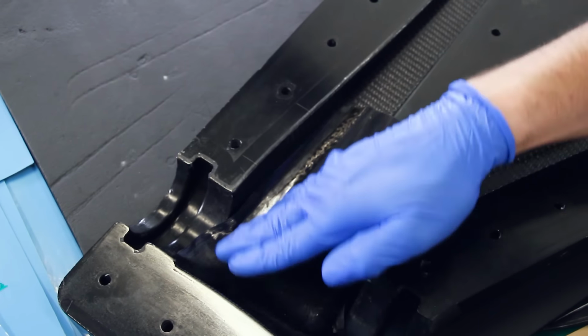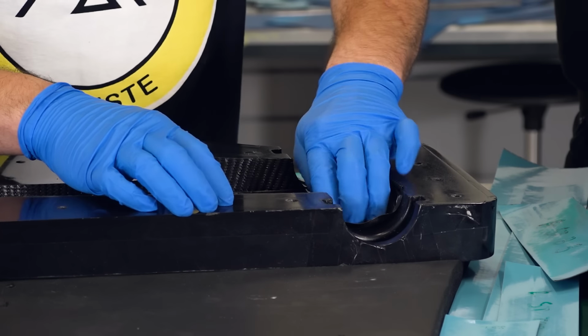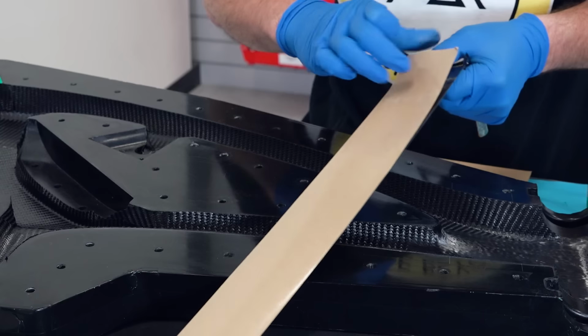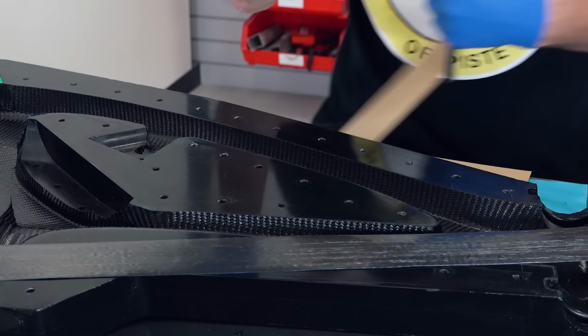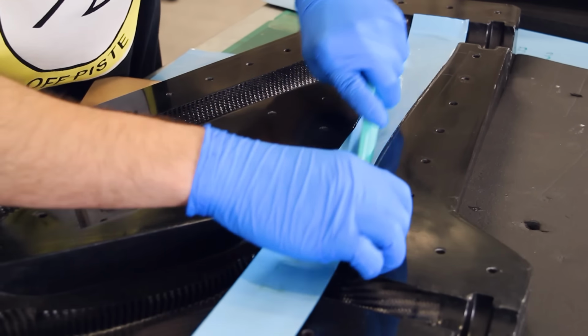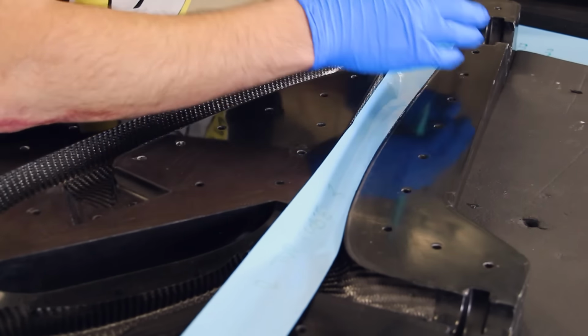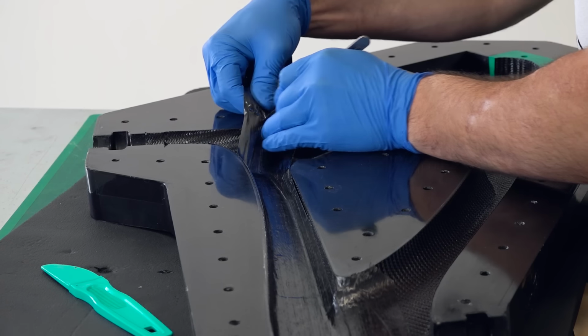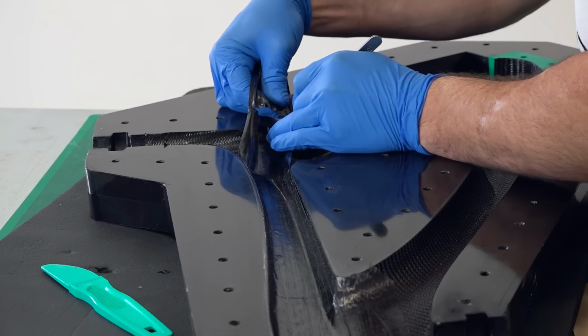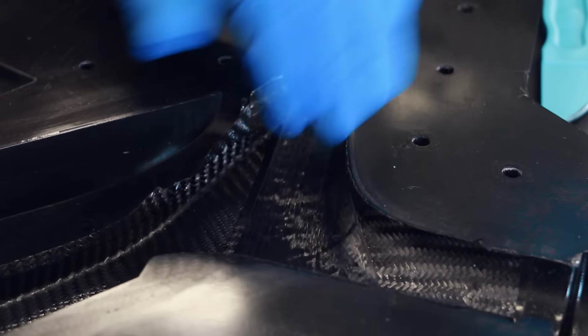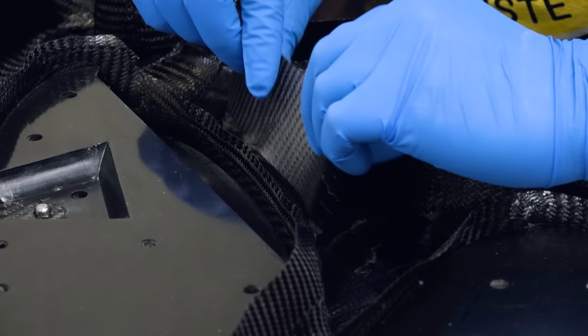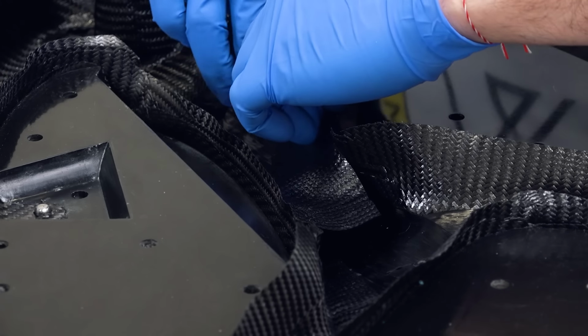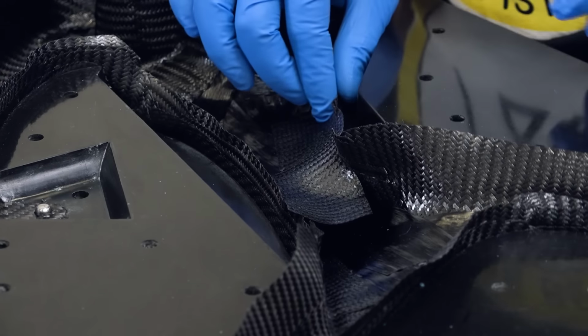As this frame already has good torsional strength and hoop strength provided by the woven surface plies, the unidirectional material is oriented straight down the length of the tubes. In the case of this build, the main tubes consist of 2 plies of 210 gram 2-2 twill on the surface, followed by 4 plies of 300 gram unidirectional, and finally backed with a further 1 ply of 210 gram 2-2 twill.